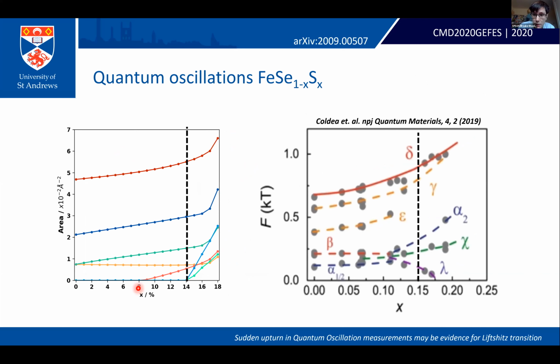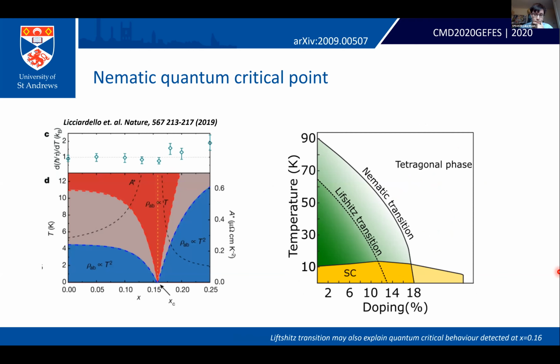And if you compare this with the experimental data in this npj Quantum Materials paper, although this wasn't the interpretation in the manuscript, if you assume that a Lifshitz transition occurs at about 15% sulfur doping, these data points are entirely consistent with a sudden sharp upturn that occurs beyond this Lifshitz transition. Moreover, this may also be able to explain why recent resistivity measurements have detected evidence of quantum criticality occurring at about 16% sulfur doping when the structural transition doesn't end until about 17–18%. Assuming that these guys got their doping levels correct, then this could just be evidence for the Lifshitz transition.